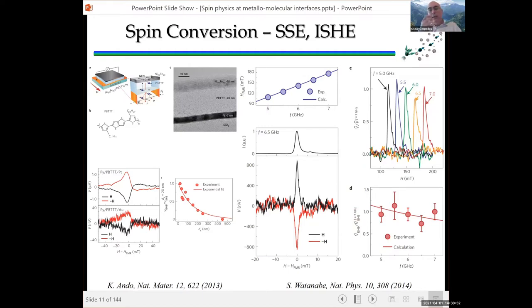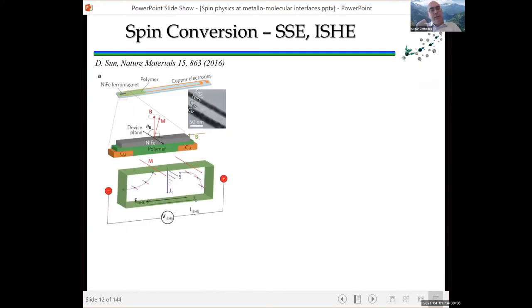Again, the group of Vardeny in Utah then decided that there was a better way of doing this. Rather than using conventional FMR, they were going to use pulse FMR, where they can send a much larger microwave current down a waveguide to generate a larger spin current and therefore a larger inverse spin Hall effect. And they did this with many different molecules.